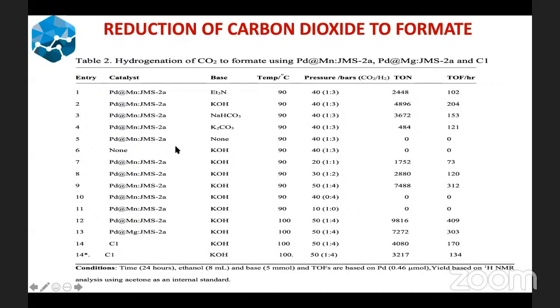And of course, with potassium carbonate, you can clearly see that the turnover number was very, very low. And again, in the absence of a base, we don't see any formate being formed. So this also confirms that the base, and in this case, an inorganic base, is very important in this reaction. And then in the absence of a catalyst, I think these are control experiments, again, we are not getting any formate being produced.